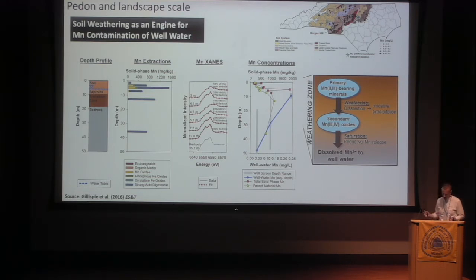And this study used a combination of field, laboratory, X-ray spectroscopic, and geospatial analyses to show how manganese is moving from the fractured bedrock into the groundwater zone, showing that weathering of the bedrock cycles manganese between primary minerals and secondary manganese oxides, and in that process resulting in the release of manganese into the groundwater. And being able to make that link from what's happening at a small scale out to a larger scale.